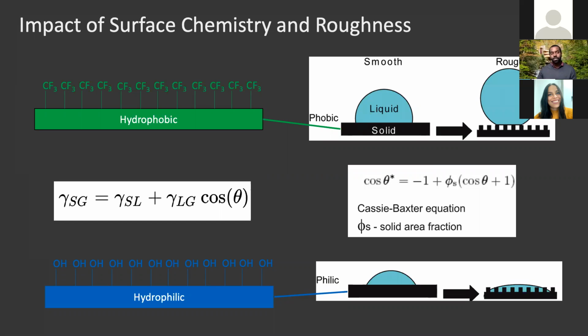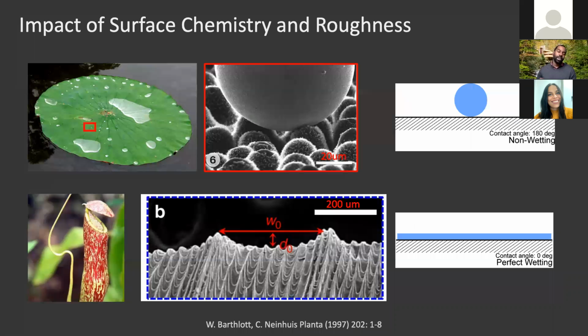So if you start adding some roughness to it, conceptually, if you have a surface that is hydrophobic, and then you start to increase the surface area that the liquid is interacting with, you'll go from a hydrophobic to an even more hydrophobic system. So if you design your surfaces in really precise or unique ways, you could increase how much water doesn't like the surface just by changing the roughness with a given chemistry. You can also do the converse. If you have a surface that likes water and you start to roughen it, now it's going to attract water a lot more. And this is what we start to see in nature.